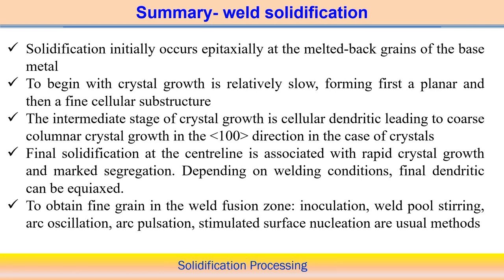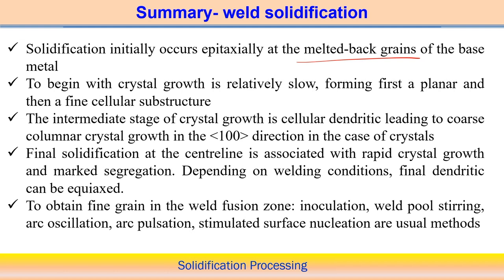Now, in summary, if you look into the weld solidification, we can say that solidification initially occurs epitaxially, as we have already discussed in the last class, starting from the melted back grains of the base metal. If crystal growth is relatively slow, initially there is a planar front, and then a fine cellular substructure is usually formed. But in the intermediate stage, cellular dendritic growth leads to a coarse columnar crystal structure.